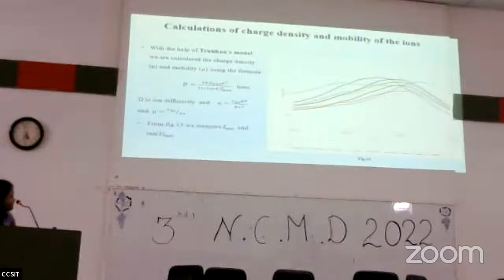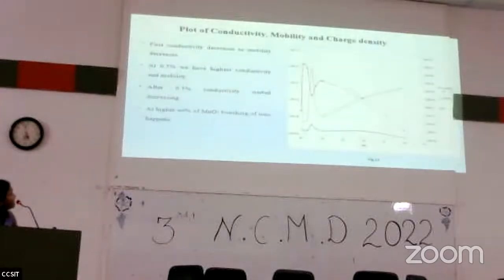I used Trukhan's model, and with the help of the plot of tan delta versus log f, I took the f max and the tan delta max values, put them in my formula, and then calculated the charge density and the mobility. After that, I plotted three curves together: conductivity, mobility, and charge density. As you can see, first my conductivity is controlled by the mobility. As my conductivity increases, mobility also increases. After that, charge density decreases, and accordingly my conductivity also decreases.